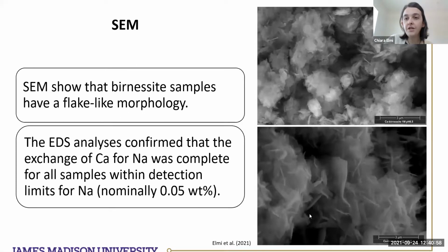That's the morphology of the Birnessite at a very small scale, 3 microns. I used scanning electron microscopy with the EDS analysis to verify that the exchange was complete. After 5 minutes in the sample, we noticed that the exchange was complete. So the exchange is extremely fast. It has this flake-like structure, and regardless of the pH, the morphology is maintained.